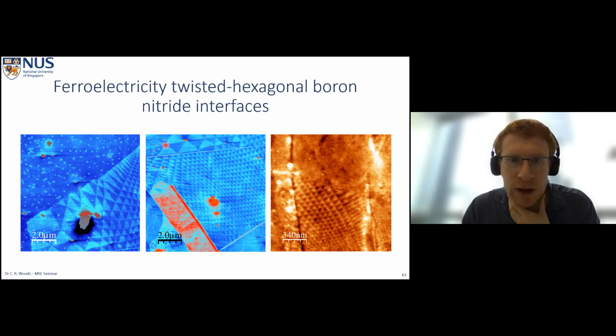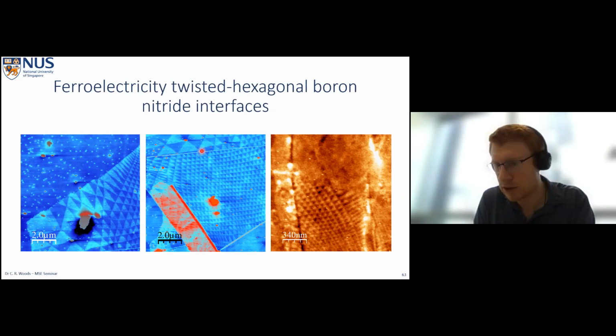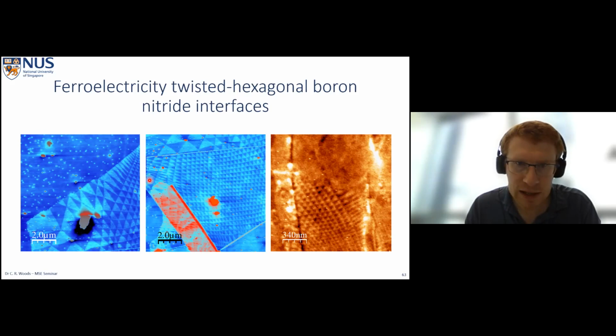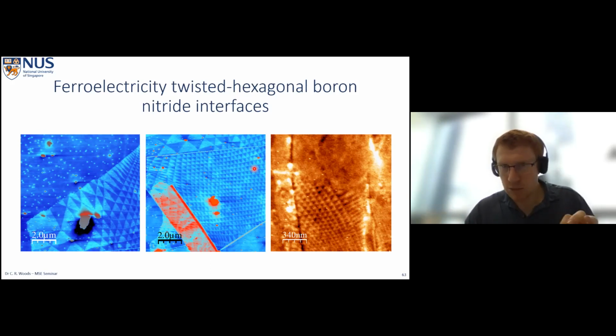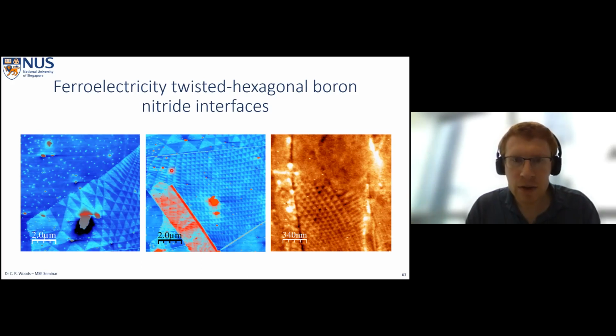So here, where we have a large periodicity, we know that the alignment between the two crystals is very good. And then we have a crease in the 4-layer, and that's what produces this discrete change from here to here. So we have a crease, the angle between the two crystals changes discretely, and that produces the discrete change in periodicity. But we also see some elongated superlattice here, and it changes as a function here. As you move them down to very, very thin, these layers become easier to include strain in. It includes some macroscopic strain, which doesn't have a discrete creasing point or folding point or something like that.